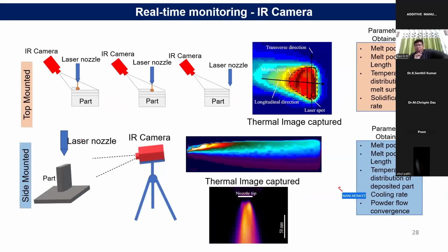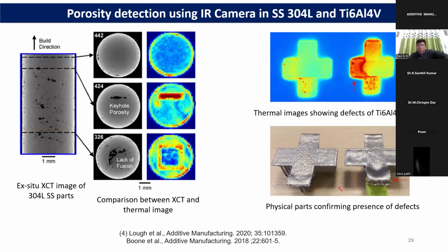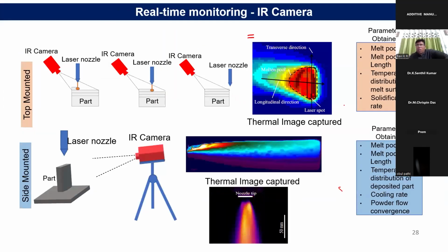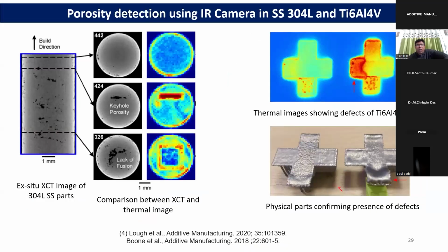On the other hand, one can easily control the defect using an IR camera, which I will discuss a little bit later. One can use an IR camera to understand the melt pool width, length, temperature distribution, solidification rate. And also you can identify whether defects are formed, whether a keyhole defect is formed, or a lack of fusion defect is formed.